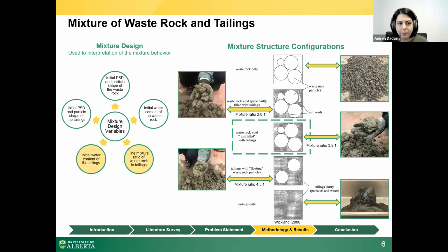Also, you can see the mixture that I built for each configuration, from waste rock only to tailings only. I calculated the just fill condition using the equation I showed you in the previous slide, based on porosity and specific gravity of a parent material. The ideal mixture ratio for the material I was working with was 3.8 waste rock to 1 tailing for the just fill condition. As you can see, for this condition, the material has enough cohesion to make a ball with it. The other conditions represent the partially filled condition, which is 2.8 waste rock to tailing, and floating condition, which is 4.5 to 1 waste rock to tailing.